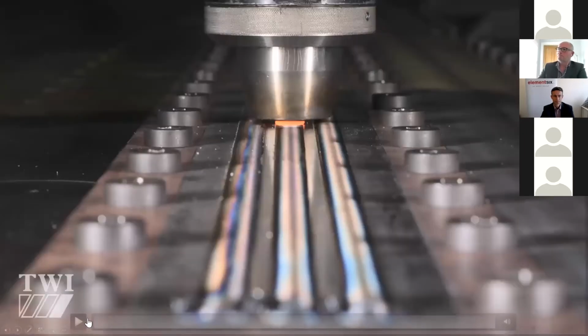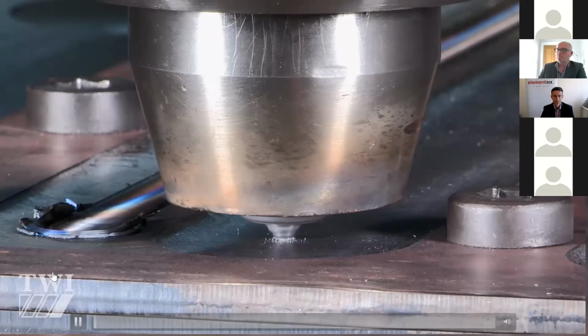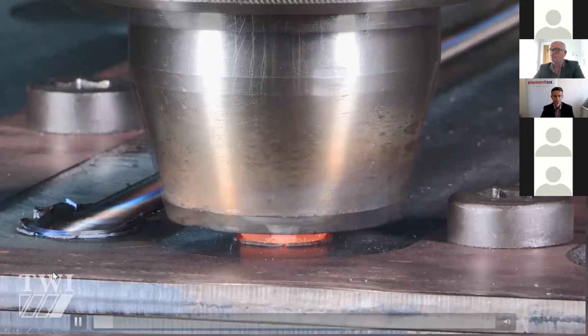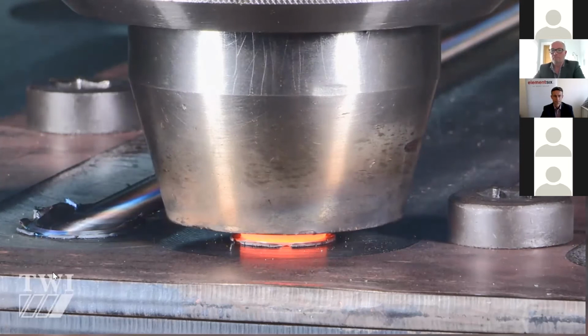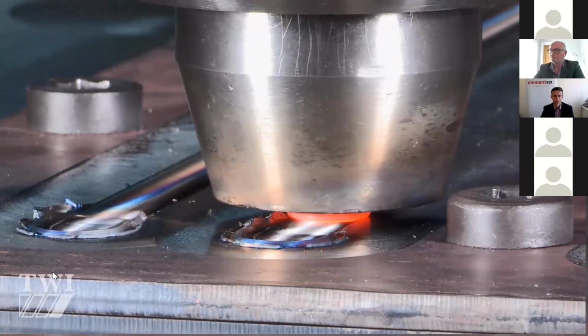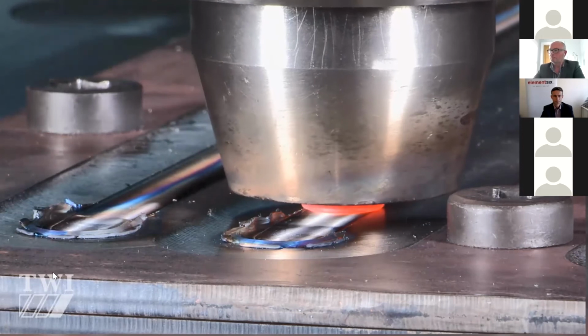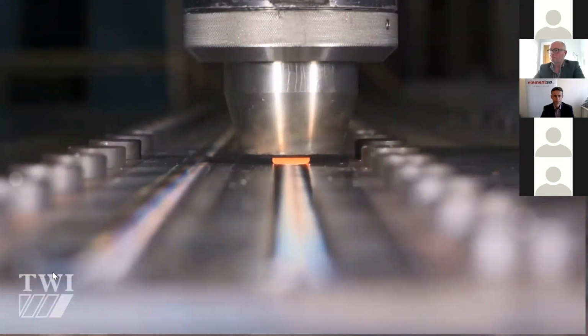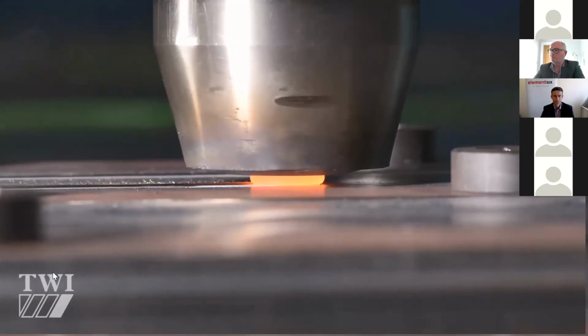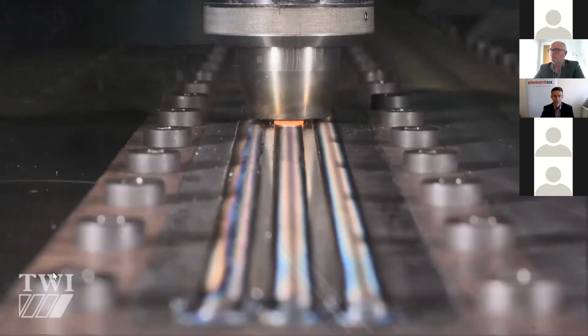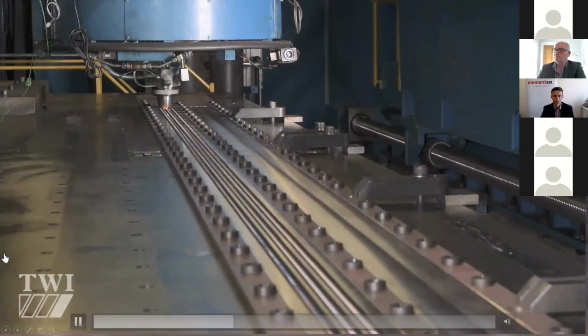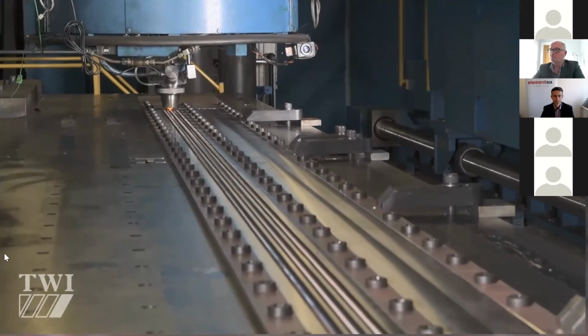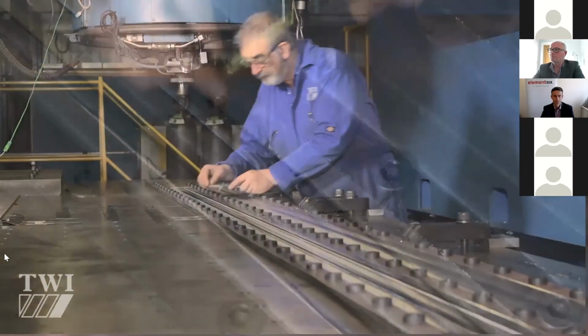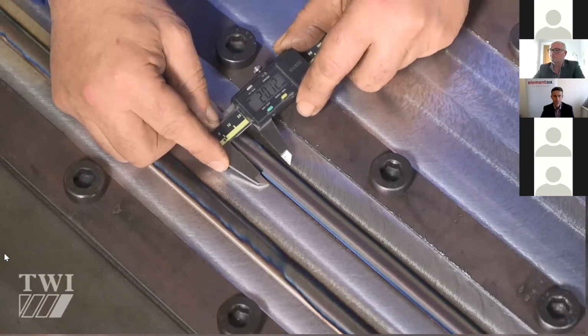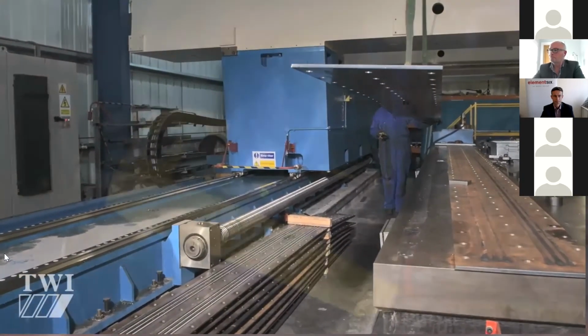Next slide, please. So if Nick runs this video for us, what we'll see is a typical friction stir weld in steel. Initially, the cold tool embeds into the steel, generates heat, and starts to traverse along the steel plate. As you'll see here, we are making multiple welds in the steel plate, effectively trying to wear out the tool. We're doing multiple welds side by side. We're seeing very little distortion. And as you can see, the friction stir welding process has no ultraviolet, no sparks, no fumes. It gives a very nice, consistent weld surface.